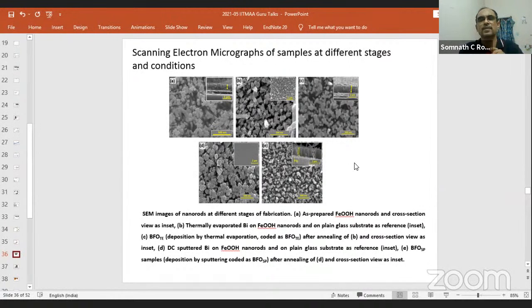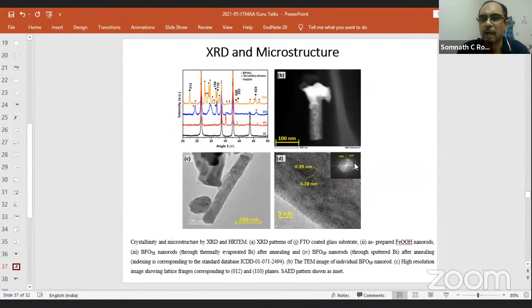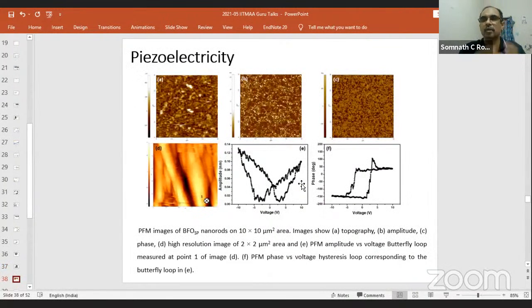So this work is still in progress, because of the phase purity. As I said, when I want to use some material for some technological application, you want the material in a pure phase, as I mentioned with copper oxide. The problem with this bismuth ferrite is that we still don't have a very pure phase. There's still a mixture of bismuth ferrite and another phase. But of course, in a single rod, the majority of the phase is bismuth ferrite. We have done X-ray diffraction analysis, transmission electron microscopy and scanning electron microscopy to prove that most of the length of a single rod had BiFeO3. But we also detected phases of Bi2Fe4O9, which is an impurity phase.